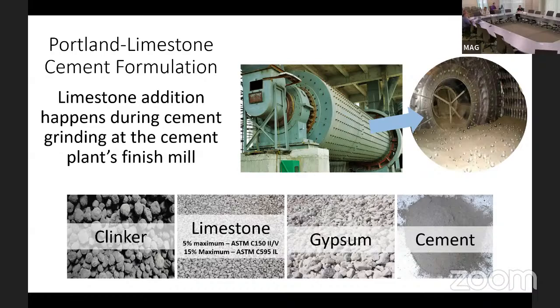So clinker is the player here that has the connection with the CO2 footprint. In most cements here, you can see with C150, you have 5% limestone. So you're looking at say 85% clinker, say 90% clinker, 5% limestone, and 5% gypsum. Gypsum is calcium sulfate. Calcium sulfate regulates the set time of cement. So you're looking at 5% limestone, 5% gypsum with that 90% clinker. That is what gives you a Portland C150 cement.